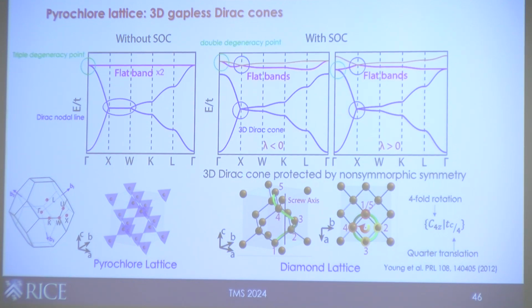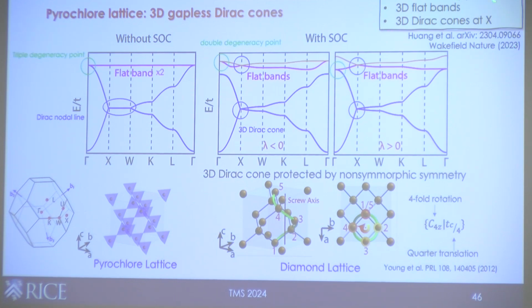So the key point is that there are 2 signatures in the electronic structure associated with the pyrochlore. You end up with flat bands, which are flat, with quenched hopping in Kx, Ky, and Kz, so that's why we call it a 3D flat band. And then you also have band crossings at the X point in the Brillouin zone. Every single band crossing, as long as the band crosses, will be a 3D gapless Dirac point in the presence of SOC. We discussed this in this paper.